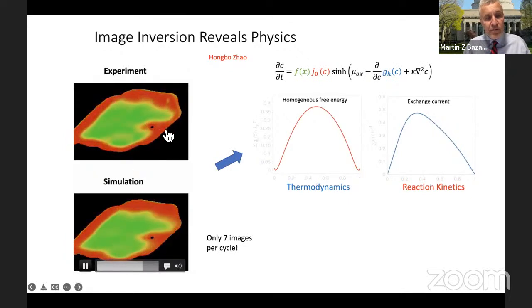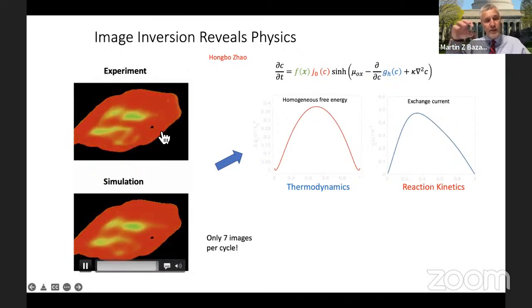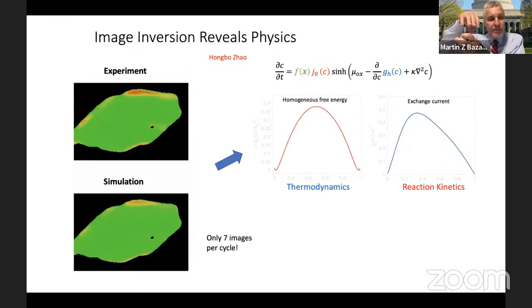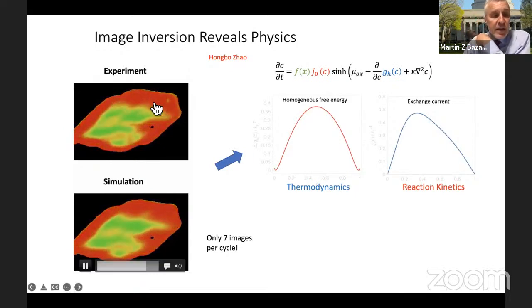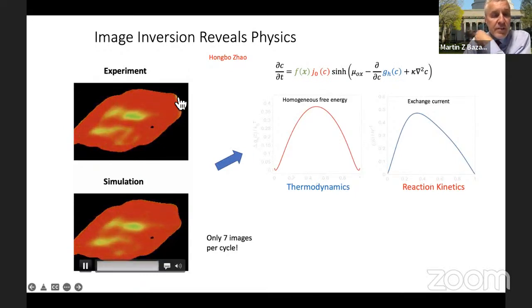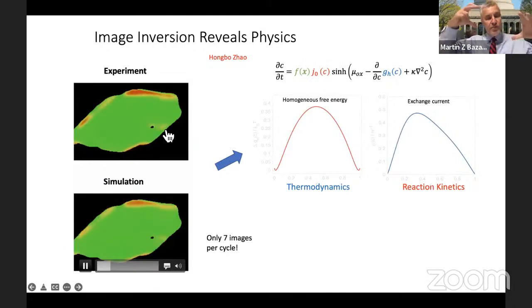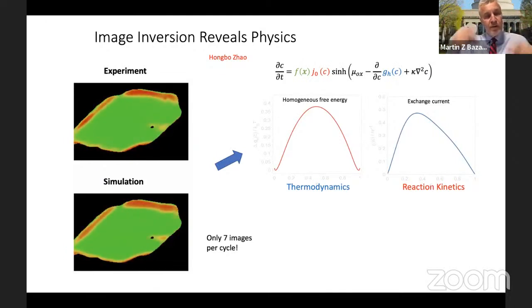So these kind of colors that are forming near the hole are showing how, partly as a result of elastic stresses, the presence of that hole is influencing where the reaction can go faster or slower. I should tell you also here that the edges of the particle, the concentrations from the experiment are given as a boundary condition of the simulation.